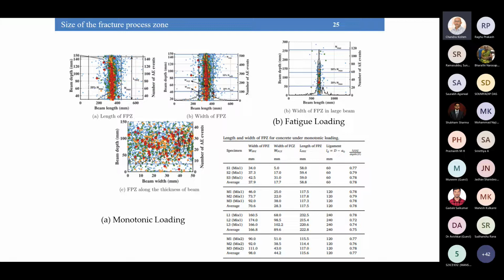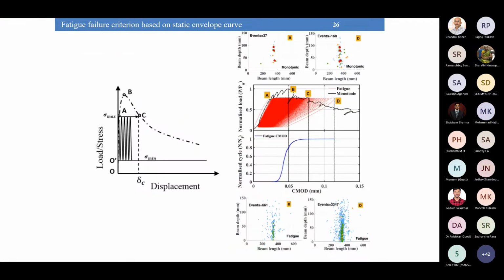But now coming to the fatigue loading, we don't see a large fracture process zone. So let's look at other results. Now, generally the fatigue failure criterion, to predict the fatigue failure, the static envelope curve is used.